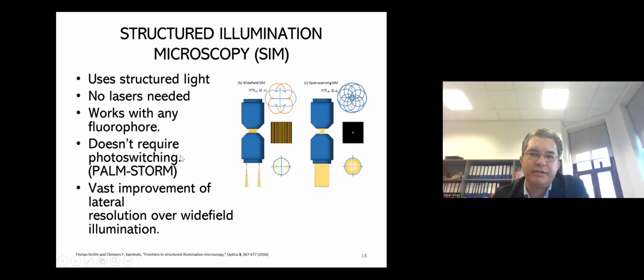We are using both approaches, stripes or dots. In conventional SIM, you use stripes and you illuminate your sample with 9 different patterns, at 3 different orientations and 3 different phases. That gives you 9 different patterns, and you record the images and do post-processing of the recorded images to achieve better resolution.